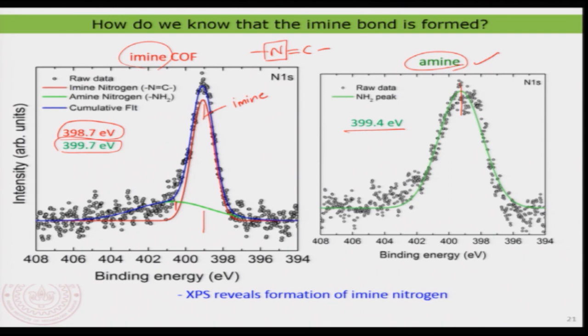This is an important characterization — just by microscopy alone you were convinced because the STM image fits the expected structure. But with the XPS measurement you can conclusively state that you have clearly formed imine nitrogen. That is a direct indication of the chemical structure of the COF formed. The combination of microscopy and chemical analysis gives a clear indication of the total chemical and microscopic structure of the two-dimensional material.